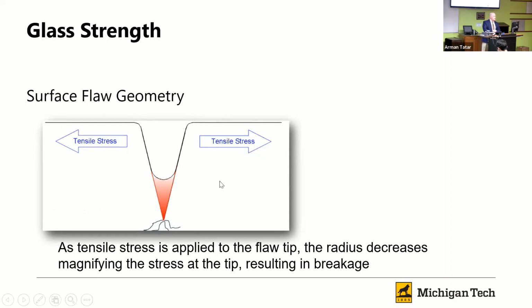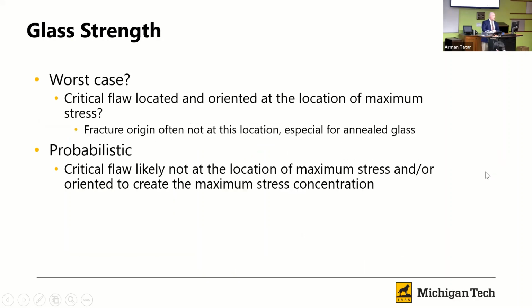So if we could eliminate these flaws, then we would have much stronger glass. And in fact, when we chemically strengthen glass, that is what they are attempting to do, is to use, among other things, certain salt mixtures to basically fill in some of these flaws where we're not allowing them to grow. They're still there, but we've kind of covered them up, if you will. All right.